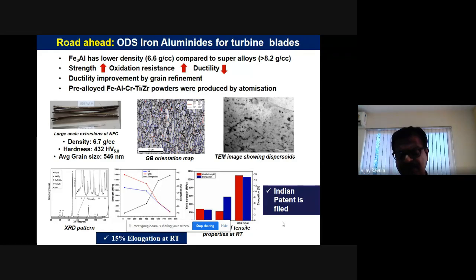But they are all expensive materials. When you use these iron aluminides, they also exhibit good oxidation resistance, and they are cheaper because you are not using nickel, vanadium, or any other costly element, and this is showing very encouraging results. We are still working on high temperature properties and cyclic stability. So it shows that iron aluminide is a potential candidate for lightweight high temperature applications, both structural and coating. This is all it is.